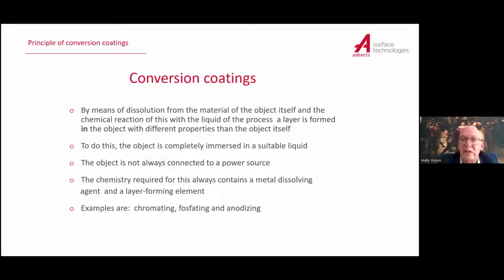What I mean here is that you also put your part completely immersed in the liquid, but when you put your part in that liquid, your part is dissolved on the top. That dissolved material, say it's aluminum, can have a reaction with a salt which is in the solution itself.